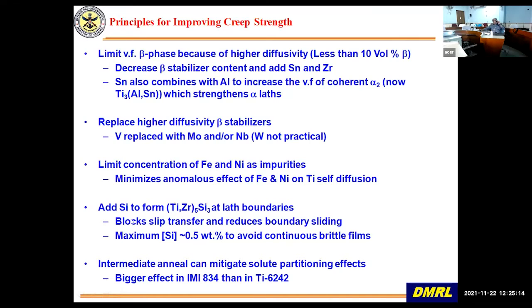And normally in high temperature titanium alloys, silicon is added because you precipitate silicide, as I showed you, and this blocks slip transfer and also reduces grain boundary sliding. So these are good for creep kind of application, but you cannot put in a lot of silicon because it also forms continuous brittle films, which renders the alloy brittle. So you have to be careful. So normally it is kept below 0.5% and most often around 0.2, 0.3 or so. And then there are other heat treatments which can also mitigate that. We will not talk about that in this lecture.